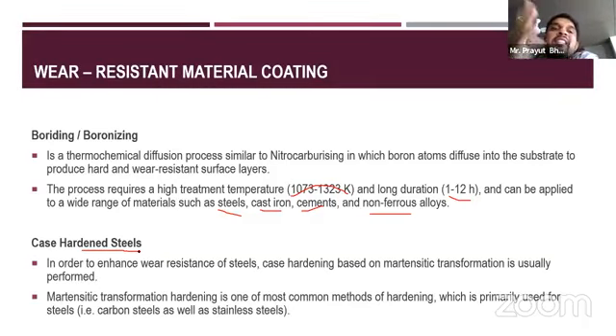So, but we can do it to an extent that it can permit. So basically, in this case, for enhanced wear resistance of steel, case hardening based on martensitic transformation is performed. Martensitic hardening is one of the most common methods of hardening, primarily used for steel. The microstructure in the steel is changed to a martensitic structure, which gives better hardness and better wear resistance. So this is case hardened steel. Again, very low cost, very effective, but not as good as the previous process that we have seen.